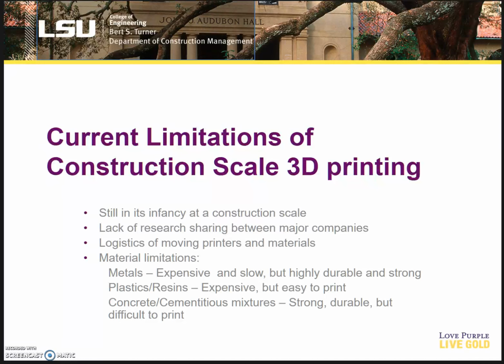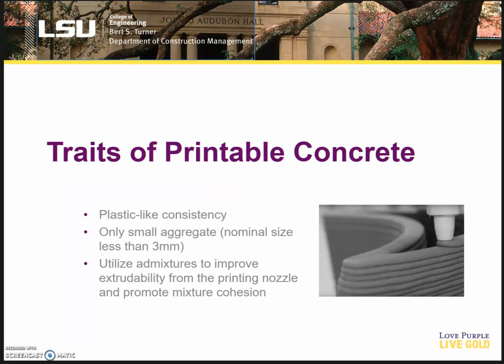Then there's concrete and cementitious mixtures. Strong and durable, just as always, but it's extremely difficult to print with due to a few specific traits. So, 3D printed concrete has a plastic-like consistency versus conventional concrete, which is meant to fill in forms or be laid into a slab. This will pretty much stay however it's extruded. It uses small aggregate sizes, a nominal size less than 3 millimeters, and then it's going to utilize admixtures to improve the extrudability of the mix, and mixtures that will promote cohesion to further improve the initial stability of the concrete.